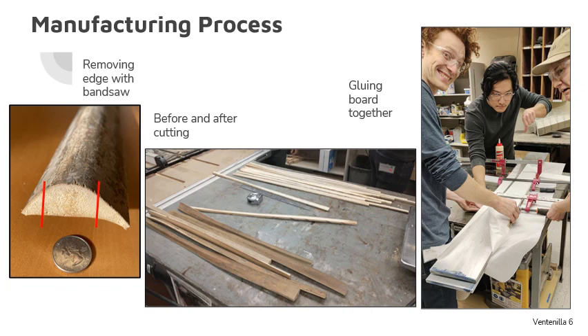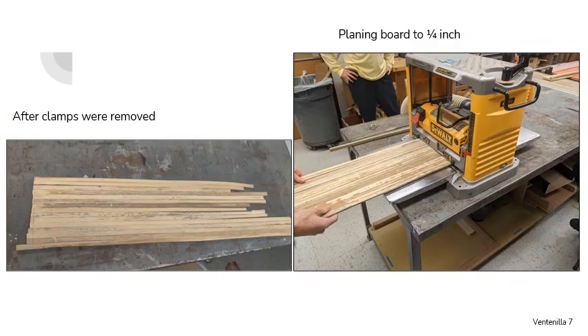Once those surfaces were made, we would run them through a table saw until they met the exact dimensions we needed for our test. In this case, they were a 1/4 inch by 1/2 inch. And in order to glue them up into a flat board, you can see on the right that we have 2 aluminum plates that we are using to clamp down the boards together in order to create a flat piece. Here's the picture of the board after it came out of the clamps. It's pretty flat, but we needed to run it through the planer in order to get to a uniform thickness. So that's pictured on the right.